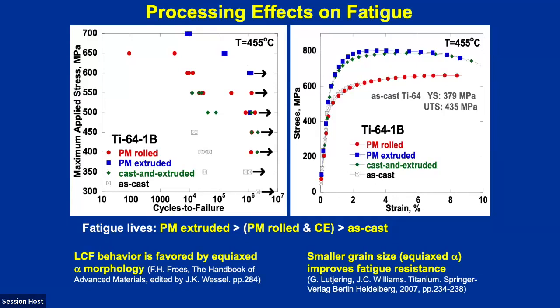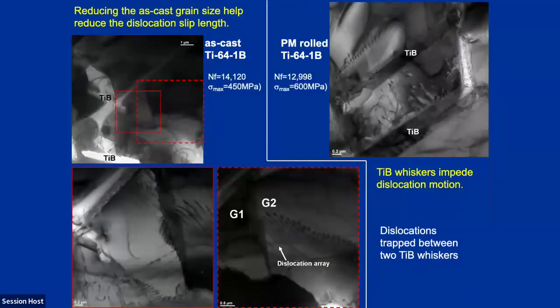So it turns out that we didn't get a debit in fatigue life at 455 degrees C with this PM extruded material, and the PM rolled, which also was subpar in tensile testing at 455 degrees C, had a slight debit in fatigue lives versus the PM extruded material. Of course, we could do more tests, but this is a good indication that we have higher fatigue threshold stresses in the PM extruded, again just a repeat of the tensile tests. So it looks like this PM extruded material would be the optimal material if you want the highest stiffness and highest mechanical performance.